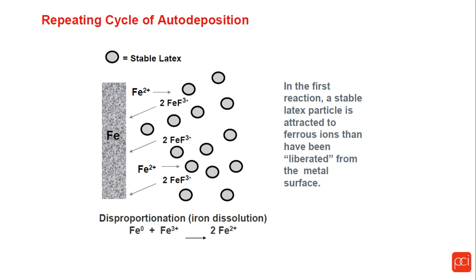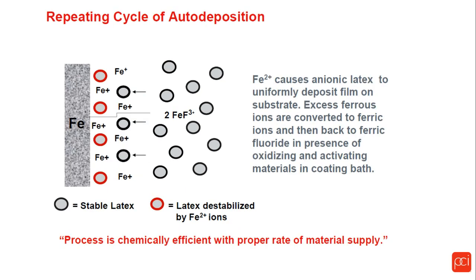This is the basic reaction that takes place with auto deposition. First, as you can see in the graphic, auto deposition works on steel substrates. It needs a source of iron for this to react. First, in the auto deposition bath, it is an acid. It will etch the steel. Some iron is removed from the part, and the iron forms a complex with the latex in the solution, and then forms back up on the part surface itself.